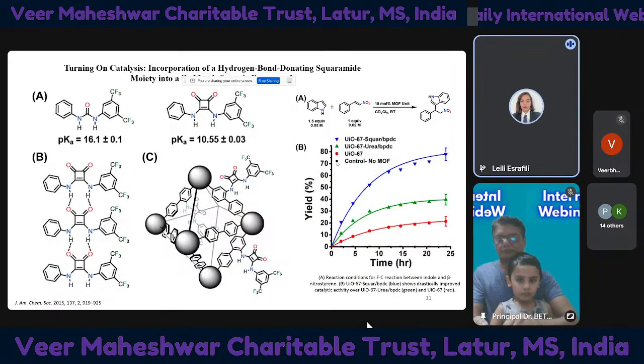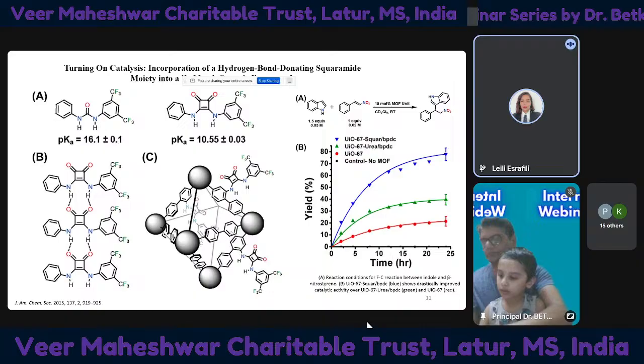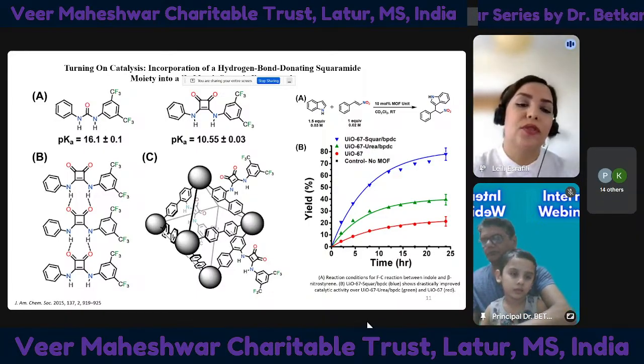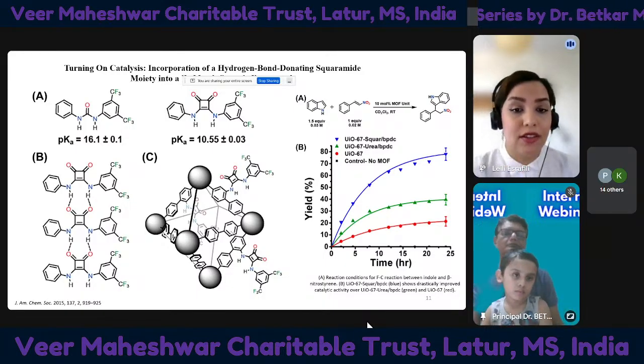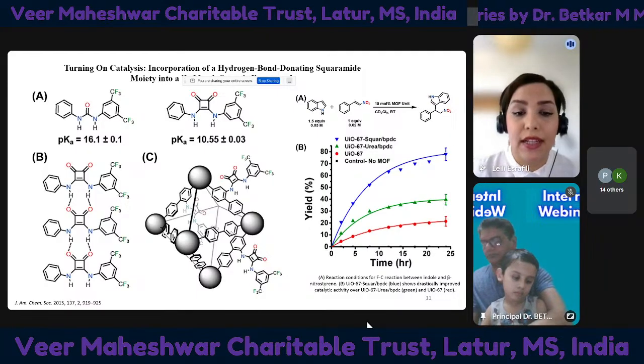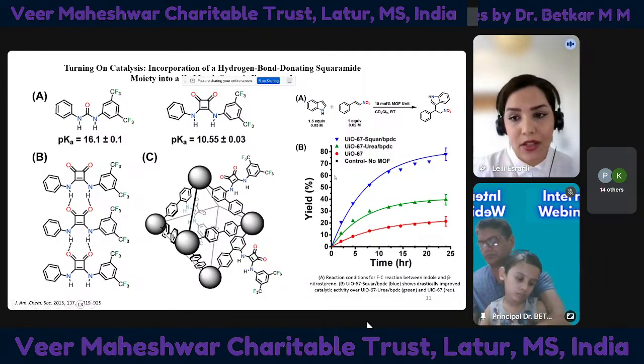In the second attempt, the same group used a more stable zirconium-based scaffold, which is UiO-67. They incorporated a squaramide hydrogen bond donor, which is stronger and more directional than urea, via post-synthetic modification. This means they had this framework of UiO-67 from the beginning. They know that it is stable, and they add squaramide functionality after synthesizing this MOF to the structure. This modification drastically improved the catalytic activity in the Friedel-Crafts reaction of indoles and beta-nitrostyrene, as you can see here.